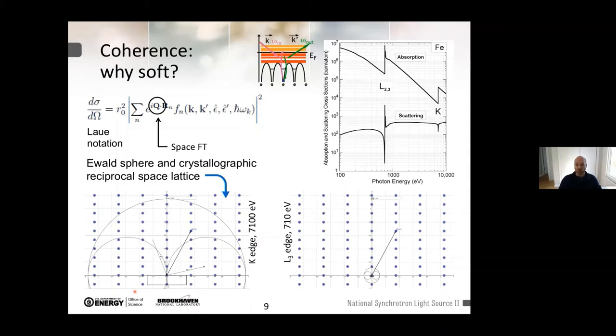Indeed, why do we want to go soft? We all know that, given the expression we gave before for the intensity of the detector, we are expecting to pay an enormous price in terms of Ewald sphere, right? Again, using the iron as we did before as a case, if you move in resonance from K edges that are here, around 7 keV, to L edges that are one order of magnitude smaller in terms of energies, as is typically the case for transition metals, and you go to the L3 at 700 eV, you see that a typical structure, that can be roughly perovskites or whatever, changes dramatically from the point of view of diffraction. In one of the cases, you populate the allowed Ewald umbrella with many points that are reachable, and so you can perform experiments. Many times, you simply can't in soft X-rays.